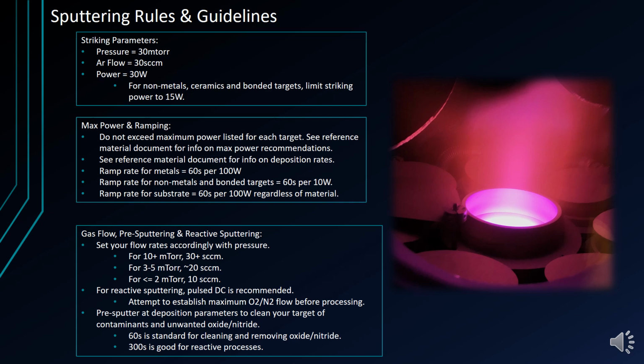When ramping, the general rule for metals is 60 seconds per 100 watts. For non-metals and bonded targets, that maximum rate is 60 seconds per 10 watts. For the substrate etch, you can treat it like a metal regardless of material, as the power density is very low by comparison due to the width of the substrate area. For flow and pressure, I attempt to choose the combination such that the position of the pressure control valve is roughly half open. This helps to keep effective pumping speeds relatively constant across different pressures. These listed combinations are general recommendations.